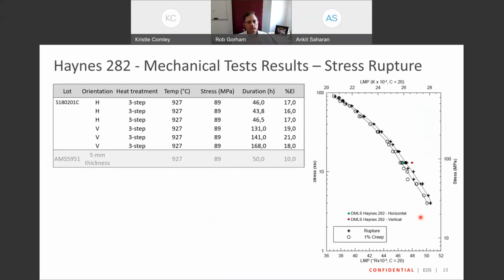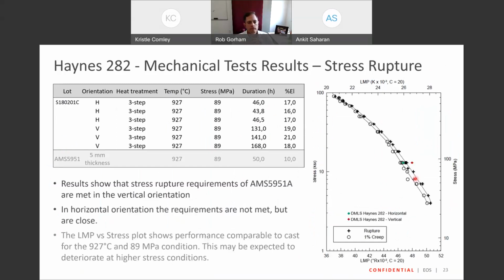And as you can see from the vertical side, we are almost there. We're kind of there and we kind of surpass it. But on the horizontal side, we're very close, but not quite there yet. So even from a stress rupturing side, that's what we've kind of found, that Haynes 282 from an additive side is a very, very viable alloy.